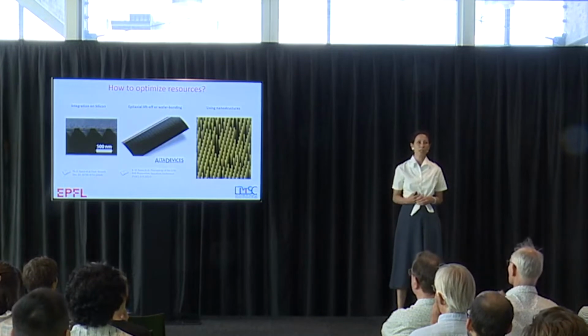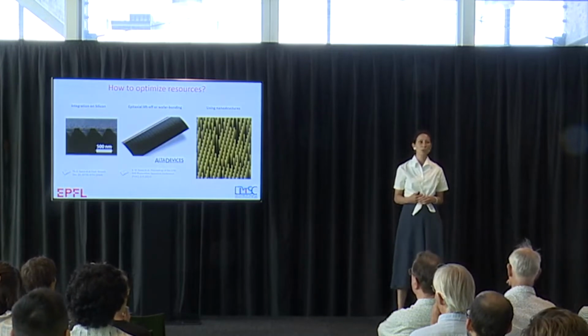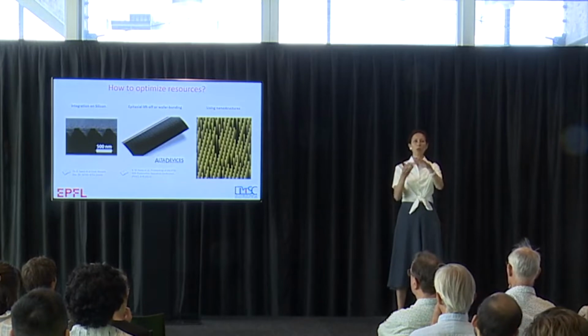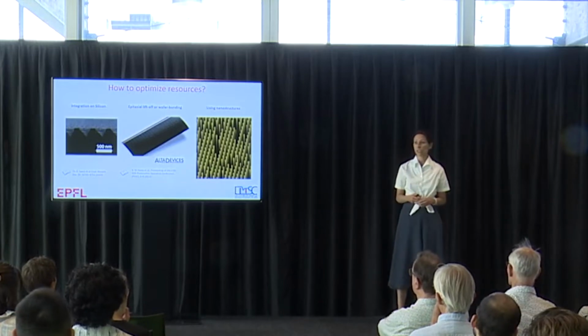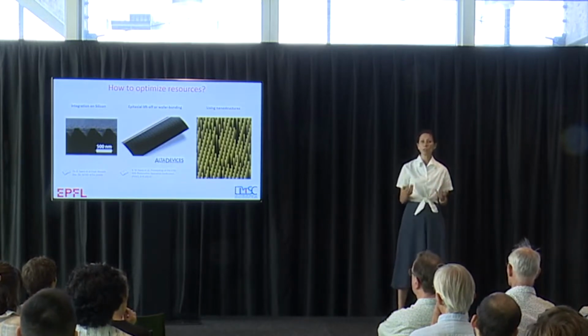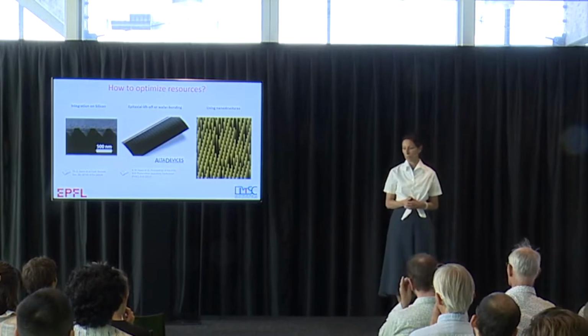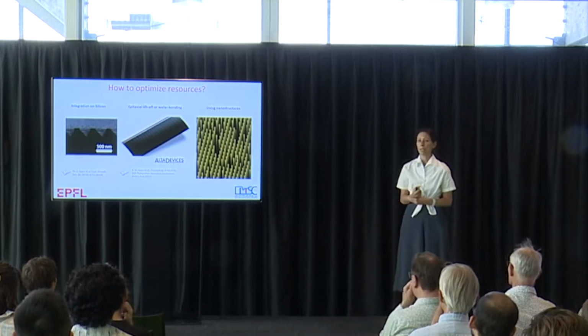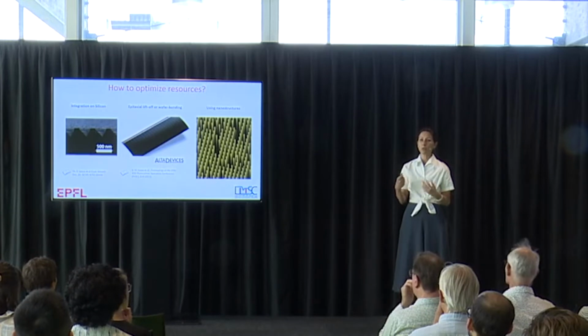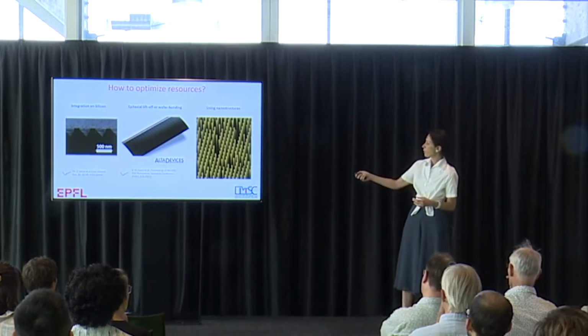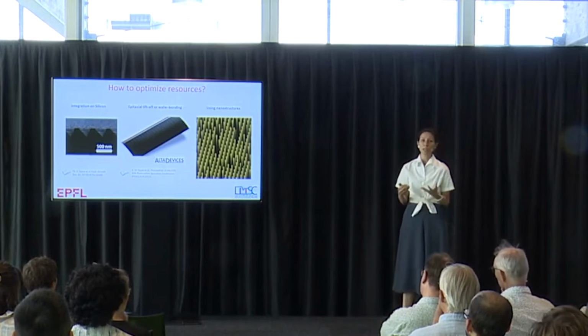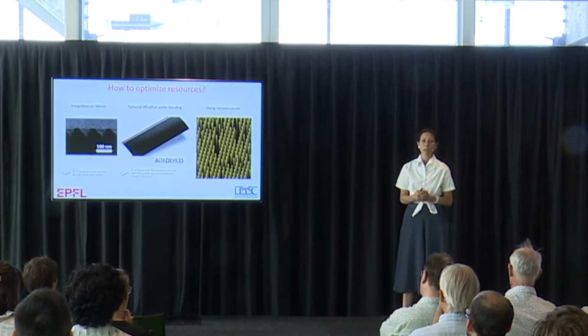Alternatives to epitaxial liftoff include what is called spalling. You start from a wafer and you can spall a piece of it, and this is very, very cheap, even cheaper than this. These are all alternatives to use very little gallium arsenide. What we also looked at for some time is nanoscale gallium arsenide, because if you look at a layer formed from these very nice nanowires, effectively you use very little of it. And here you're not restricted by what substrate you use.